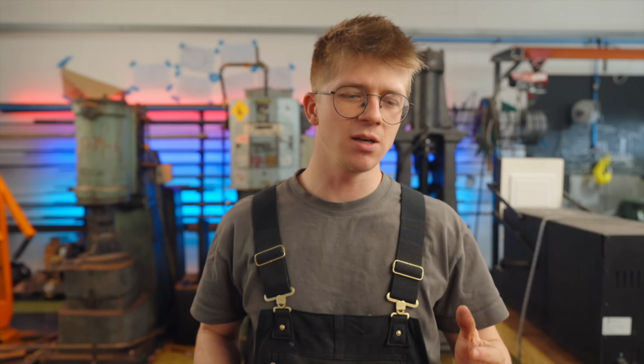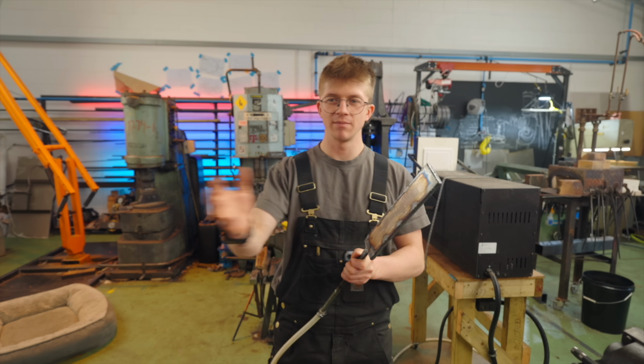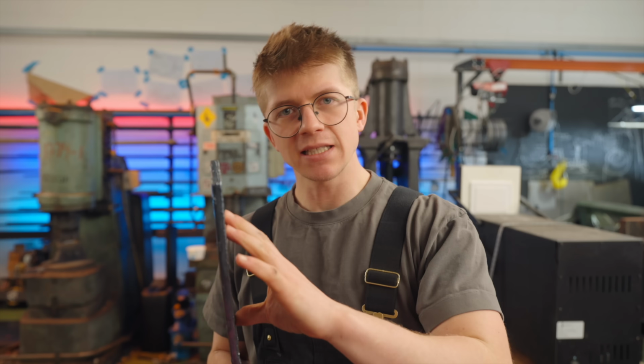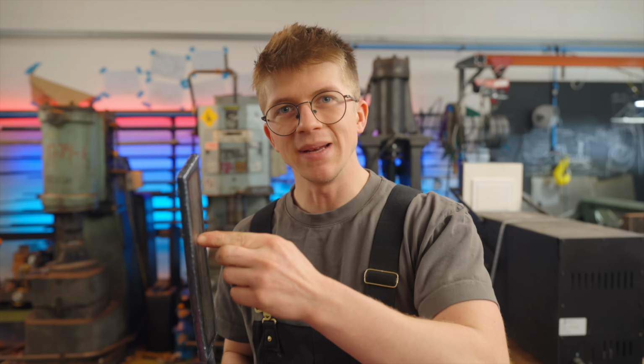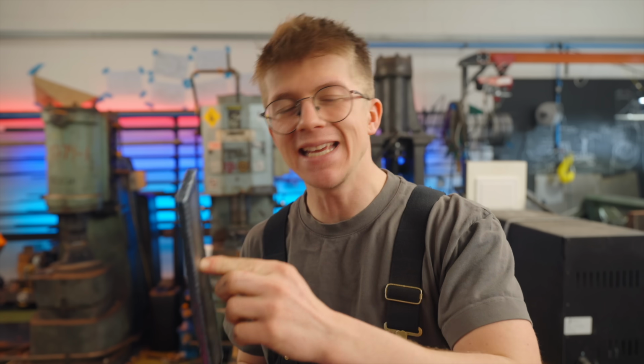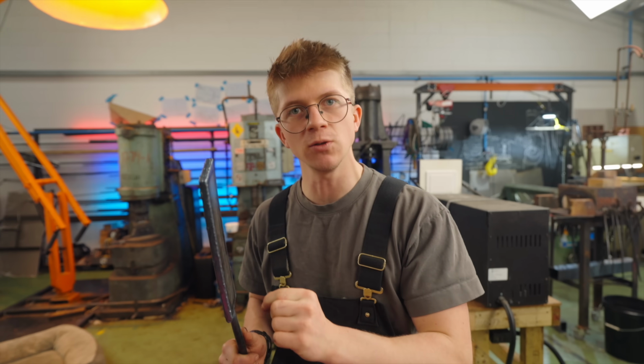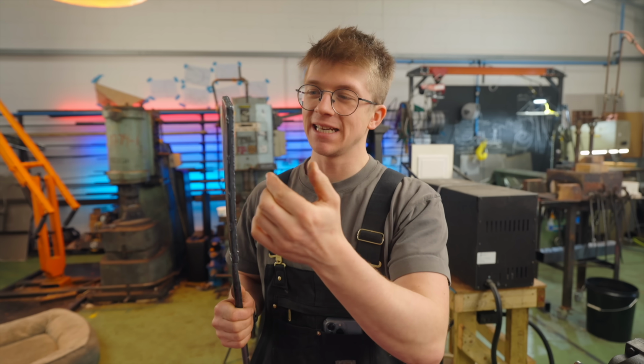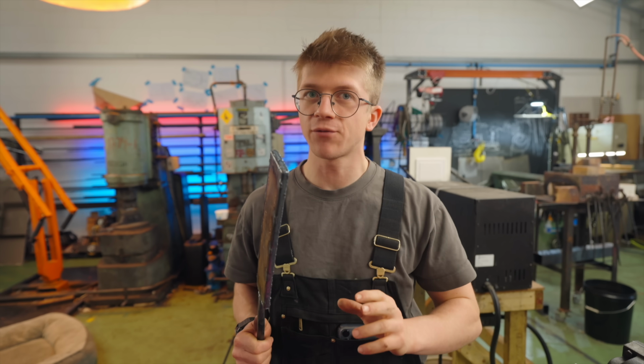Jamie, do you happen to know a little bit about the thermal conductivity of titanium? How does it compare to that of steel? Less thermally conductive than steel. Which means that temperature moves slower. So as this gets dunked into the oil, the titanium isn't able to dump the heat into the oil as quick as steel would. So it's effectively insulating the steel from the oil, stopping it from cooling quickly.